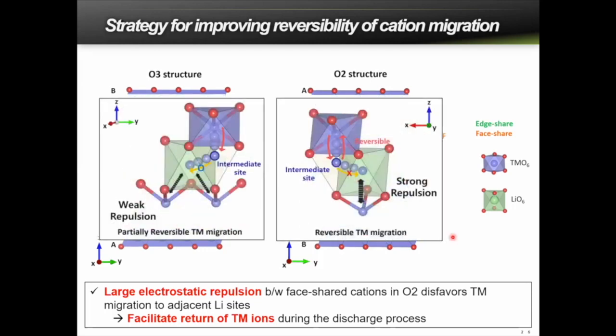If you look a little bit more closely at the local environment during the transition metal migration in these two different layered structures, they are substantially different. In the conventional O3 structure, the transition metal hops to the lithium layer via this intermediate site and jumps to the nearest octahedral site. These are the lithium layer and these are the transition metal layer. And these octahedral sites are relatively stable, and therefore this process can readily occur.